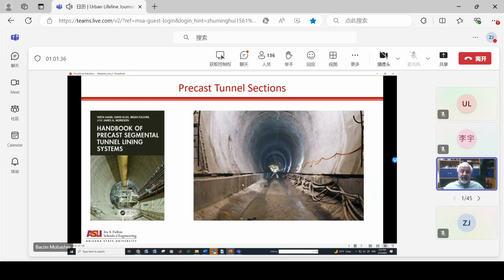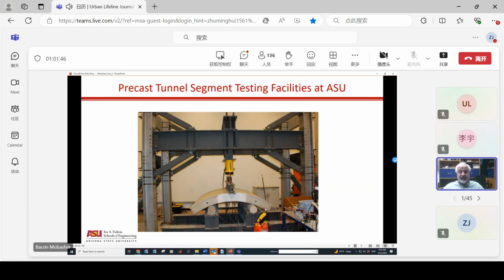I've been working in this area of precast tunnel sections where we're only using fiber reinforced concrete right now for all of the tunnel lining that are being used. And in our laboratory, we've built up a facility to basically test the flexural capacity and also axial capacity of these tunnel lining. These are using fiber concrete, somewhere between 30 to 50 kilos per cubic meter.